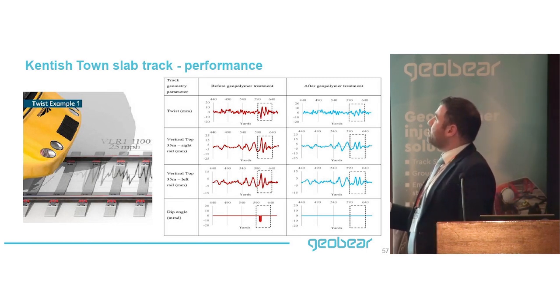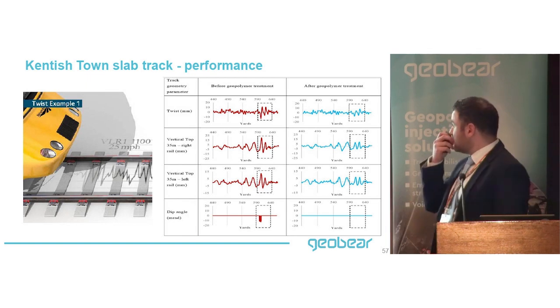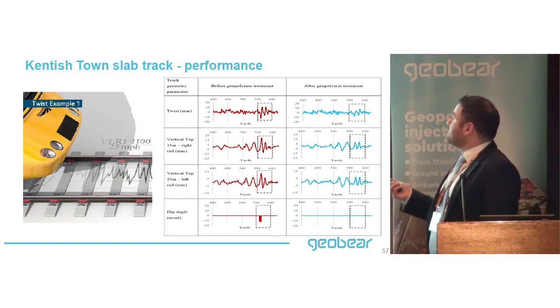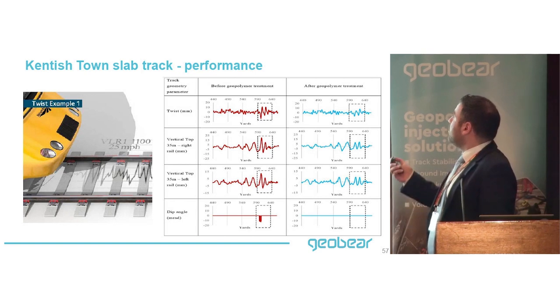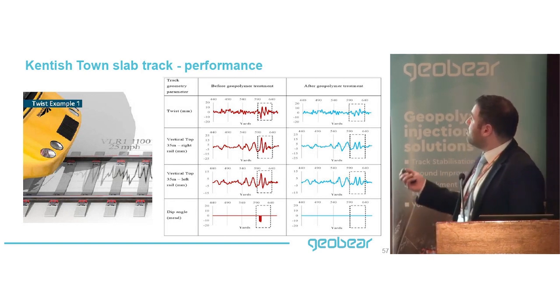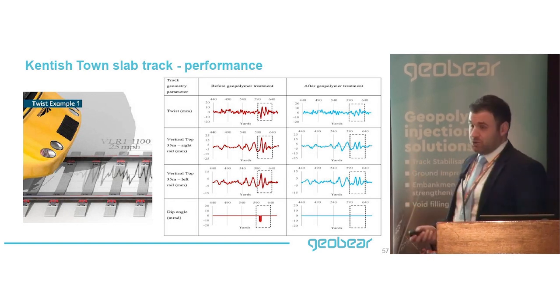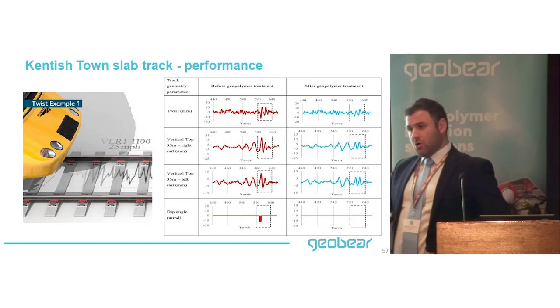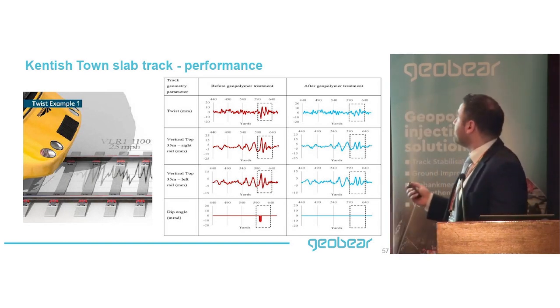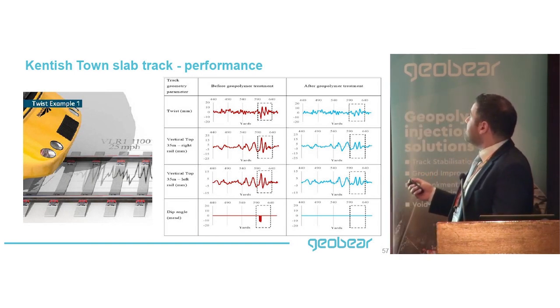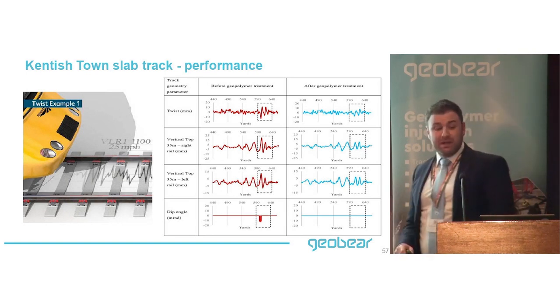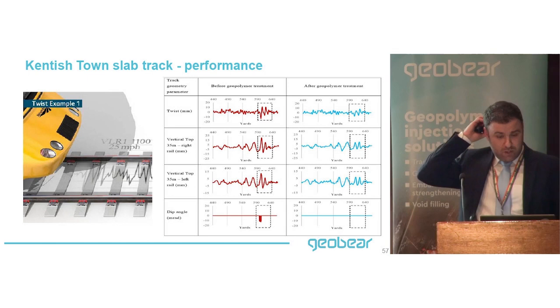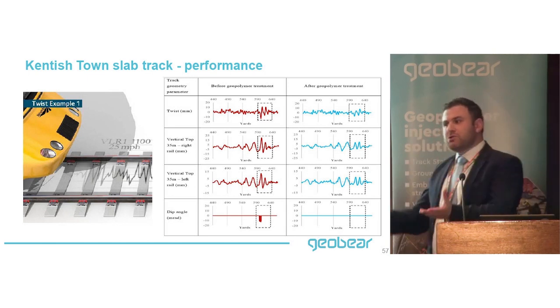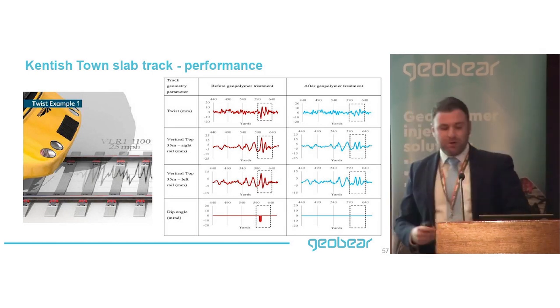You can see here where there was quite bad response, even dip angles showing up. Following the treatment and the next run, this was the resulting track geometry. We managed to strengthen the ground but also almost lift it back to the right position. You can see a significant improvement in the track geometry response after the treatment, to the point where we even eliminated the presence of dip angles. But that was part of a temporary solution, not a permanent one.